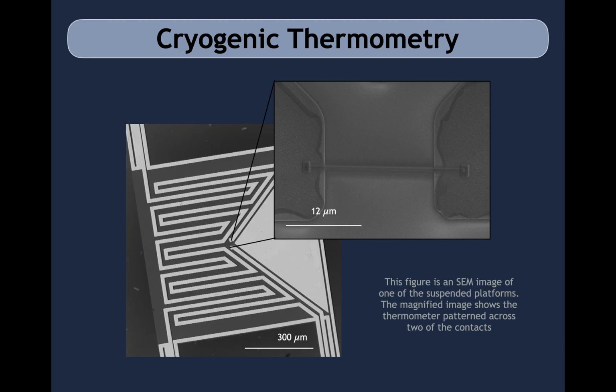These thermometers are uniquely suited for this application because they can be patterned directly onto the suspended platforms without risk of damaging them. On the slide, you can see the thermometer deposited across 2 leads on one of the suspended platforms to measure the applied temperature gradient across the silicon nitride bridge.